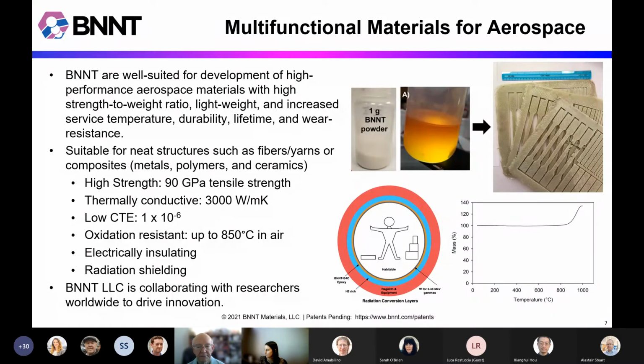On the right here, there are a few photos I've shown, an example of a powder that we've made from the boron nitride nanotubes, so that it disperses really well in an epoxy resin that was of interest to someone, so that they could make some different glass fiber reinforced parts. Those are some dog bones there you can see.